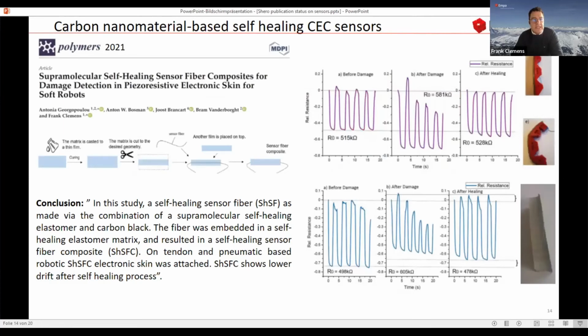Later on, we looked at what happens if we work with self-healing materials. Here you can see a self-healing fiber integrated in a self-healing matrix. This was done together with Suprapolix and the University of Brussels. And what we found out is that when you work with this kind of pneumatic actuator, where we apply a pressure, the sensor will be working under compression. Here the sensor will work under strain, and we can see that for this composite, which has been developed together with Suprapolix, the strain behavior is much better than the compression behavior. So compression is almost not detectable by the material if we have a damage inside the matrix.